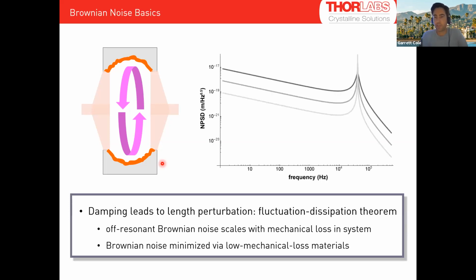So here, if I plot the total noise of one isolated mechanical resonance of that body, maybe it's the breathing mode of the spacer, maybe some flexural mode of the substrates. So I'm going to take that one mechanical resonance and I'm going to plot its noise, basically its amplitude of deflection as a function of frequency. So if you've ever done mechanics, you've seen these Bode plots, these kind of roll up to resonance and roll off. But now what I'm going to do on this plot is I'm going to change the mechanical quality factor of the elastic loss.